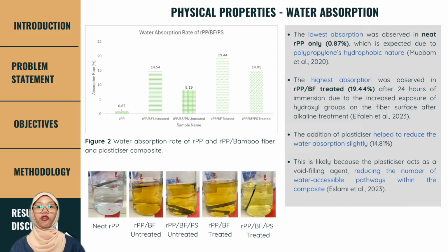Result and discussion of water absorption testing. The lowest absorption was observed in the neat RPP, only 0.87%, which is expected due to polypropylene's hydrophobic nature. The highest absorption was observed in the RPP-BF treated, which is 19.44% after 24 hours of immersion, due to increased exposure of hydroxyl groups on the fiber surface after the alkaline treatment.